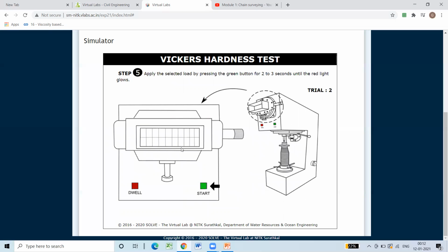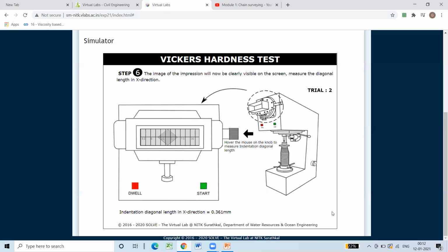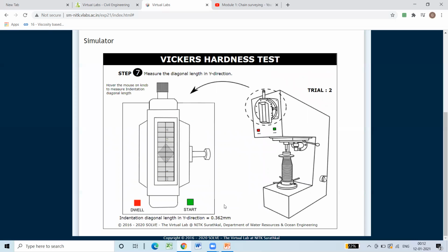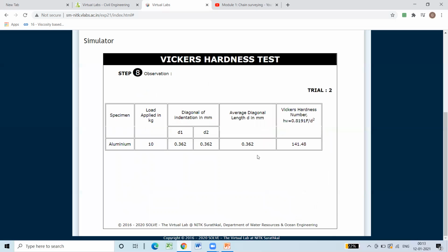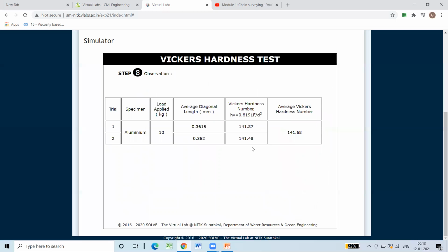In the next step, you apply the selected load for about 2 to 3 seconds by pressing the green button. So I have applied it. By using the microscope, now measure the indentation diagonals. First in the x direction, that is equal to 0.361 mm. Next measure in the vertical direction. Again that is equal to 0.362 mm. And take the average in the next step, that is equal to 0.362 mm.